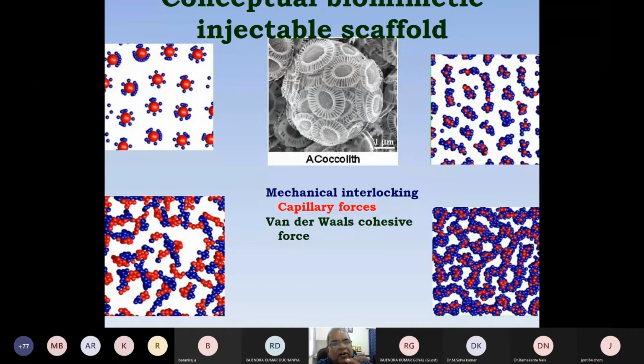What we thought: our hydroxyapatite, which is biomimetically synthesized, you can think of those red particles as hydroxyapatite. It is synthesized under a polymer matrix, which has a functional group on the surface. So they are functionalized on the surface. So I thought if we convert it into a paste and put them together, due to the pressure they can come along, they can